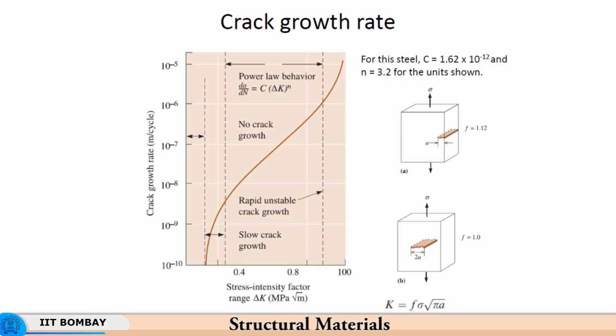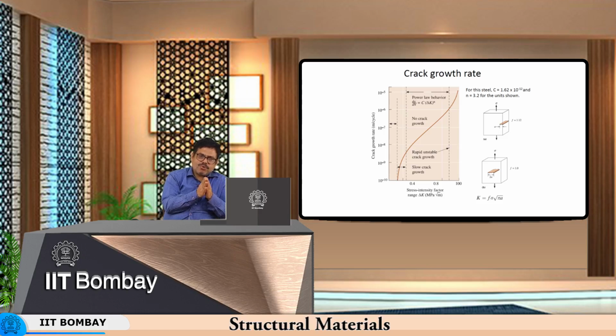Now, after the stress intensification continues to increase, as the stress intensity grows, then there is a rapid, or let us say power law type of crack growth, more rapid crack growth. As you see the slope over here, there is a power law being followed. So, here you have C into delta k to the power n as the fast crack growth, and then beyond a certain value of delta k, because now as the crack grows delta k is changing. Sigma root of pi a is our value of k. So, as the value of a keeps on changing, you will have a change in value of k. Naturally delta k with every crack advancement will result in a new value of the rate of propagation of the crack. So, dA by dN defines how much is going to be the change in the length of the crack per unit cycle, and that is what the beach marks or the striations on the surface of the fracture will indicate to you.